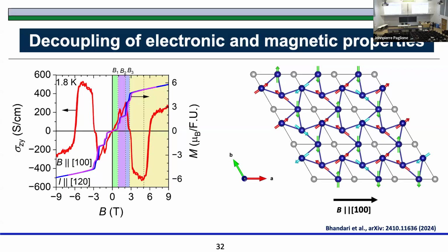Now apply magnetic field along this direction, not along this direction. Okay, that was studied by other groups also. This was not studied by any group, interestingly. We found that there are these similar features. There is a drop, maybe there is a change in the electronic structure here, and then it tries to kind of follow the same behavior as in the other direction. But above this 5 Tesla, it goes again boom up, where there is no change in the magnetization. So this is a puzzle still. We don't understand why this is happening, but this is a very unusual feature.